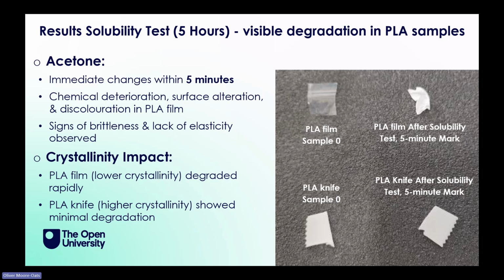So one aspect that can affect this is the crystallinity, like we mentioned before. The theory is that because the film is less crystallized, so it's more amorphous, acetone can penetrate better and degrade the product, leaching out some components, like plasticizer. Plasticizer is something that they use in products to change some of the parameters, for example, to make them more elastic or clear. That's why we see some change in color as well. While the knife, on the other hand, which was more crystalline, if you remember the graph, didn't have visible degradation or damage.